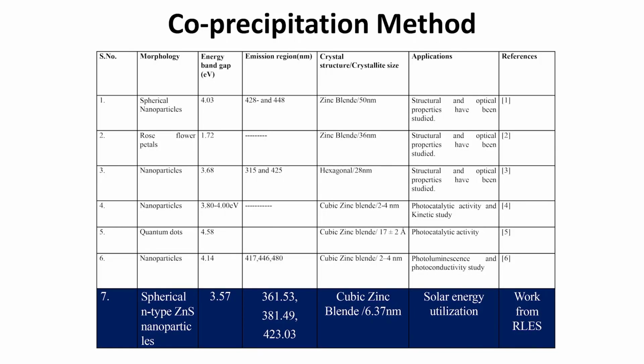In the co-precipitation method, we have synthesized various morphologies of ZnS, and these morphologies are spherical nanoparticles, rose flower petal nanoparticles, other nanoparticles with band gap 3.80 to 4, quantum dots of energy band gap 4.58, nanoparticles of band gap 4.14 electron volt, and the spherical n-type ZnS nanoparticles which we have developed in our lab. It has a band gap of 3.57, and the emission region ranges from 361.53, 381.49,